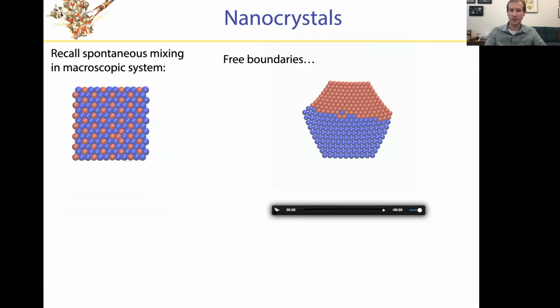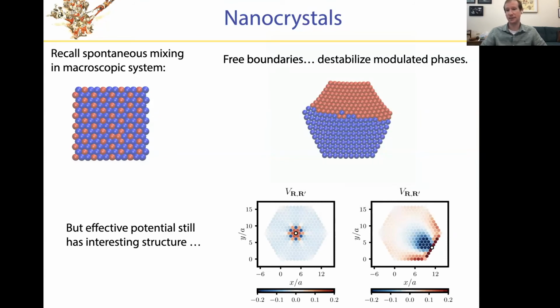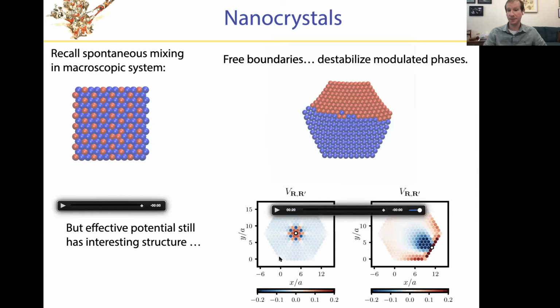And what we find is that when we introduce free boundaries, these materials don't mix, that those interesting exotic phases that I was just showing you aren't present at equilibrium, which at first was kind of sad because we were excited we had discovered these generic exotic modulated order phases. And now they seem not to be pertinent on the nanoscale because the boundary conditions are different. But if we look in detail, we can calculate effective interactions among these red and blue particles and get a sense for whether a blue thing likes to be surrounded by red or by blue as a consequence of all these elastic interactions. This effective potential still has a very interesting spatial structure to it, highly reminiscent of what we saw in the macroscopic case, even in a nanocrystal.